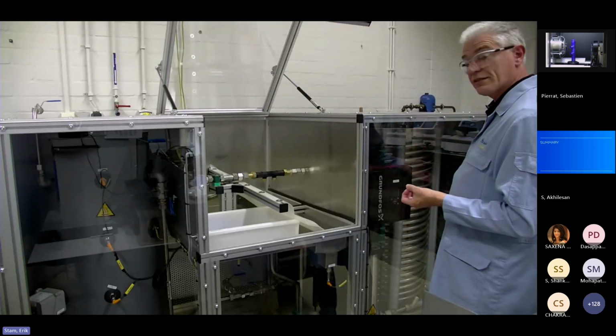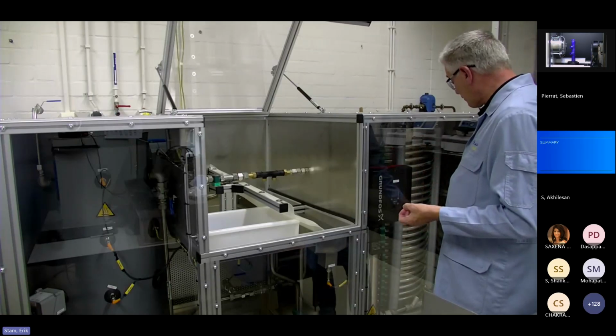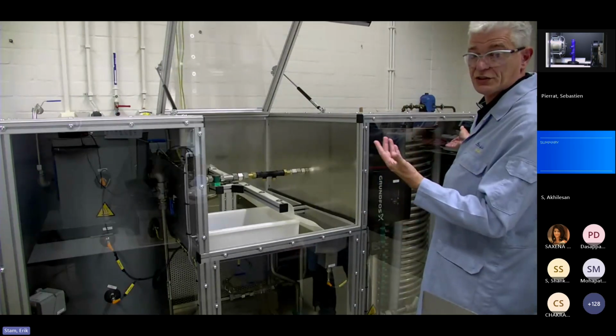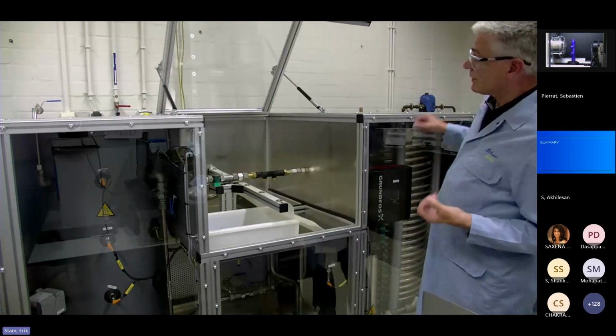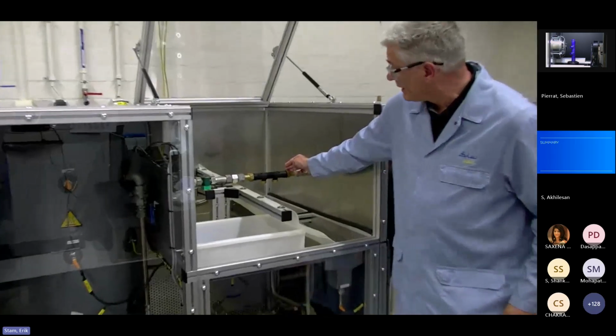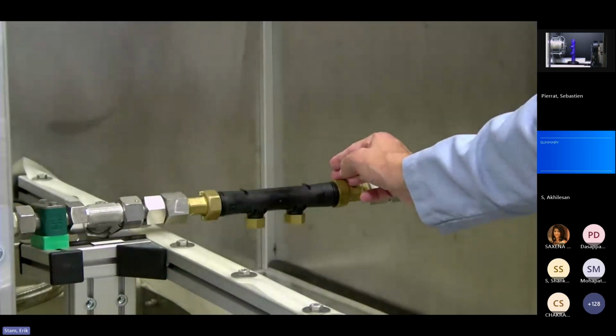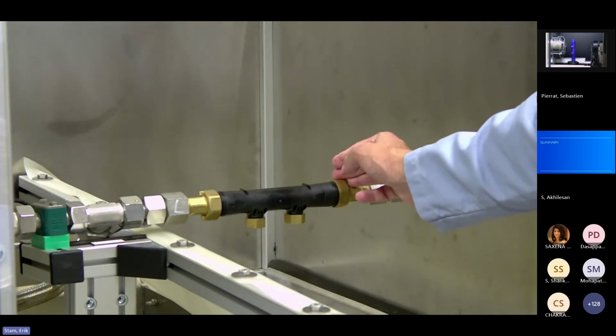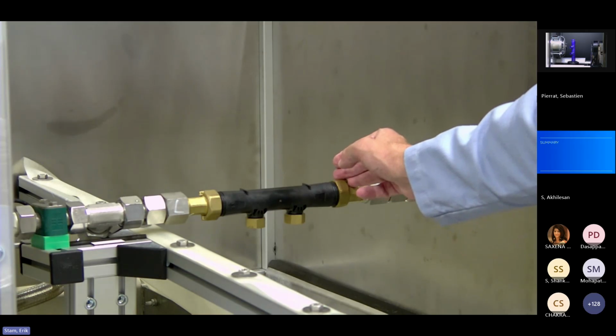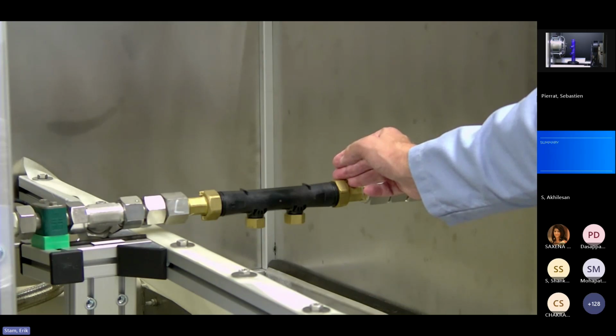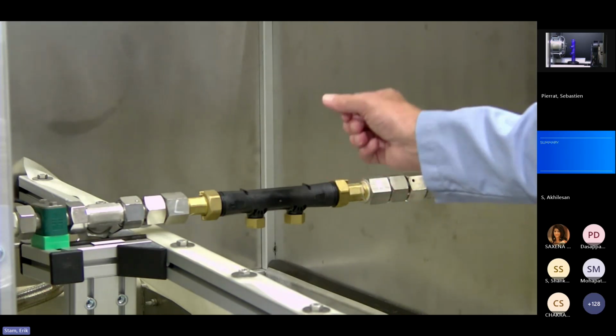At the moment, I'm standing at the water hammer test. The water hammer test involves a large coil which generates a large volume of water. This water flows through this sample here, and at one moment the water comes to a sudden standstill. There's a valve which closes, and due to the closure of the valve, this will generate a peak of 16 to 25 bar, and this is repeated over time. So some customers require to pass 100,000 cycles, and then the application is fulfilling the requirements set by the customer. But this is just one type of fatigue test, and there are more fatigue tests, and I will show you the next one.